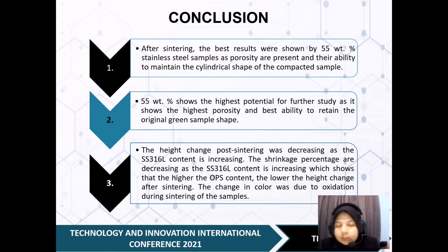So lastly, for the conclusion, after sintering, the best result was shown by the 55% stainless steel samples as porosity is present and they maintain the cylindrical shape of the compacted samples. So 55% shows the highest potential for further study as it shows the highest porosity and the best ability to retain the original green sample shape. The height change post-sintering decreased as the stainless steel content increased. The shrinkage percentage decreases as the stainless steel content increases, which shows that the higher the OPS content, the lower the height change after sintering. The change in color was due to oxidation during sintering of the samples.